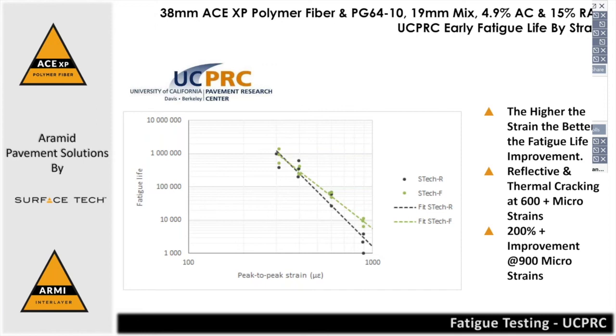And that you can begin to see under the tire load. It's believed to be somewhere around 300-500 microstrain. Once you get up near 1,000, you start to approach movement that you could even see on bridge decks, and up to 2,000, which the interlayer I mentioned was even designed at.